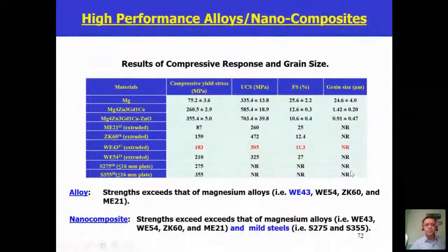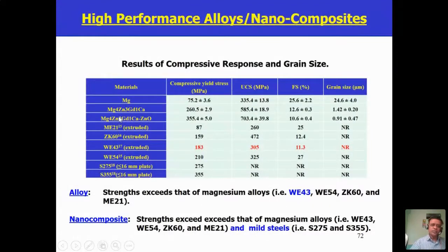We also develop new materials. Now this slide, for example, shows we developed a material with zinc, gadolinium, and calcium. And you see this property, 260 megapascal, 585 megapascal, and failure strain in this case does not go up, but it stays beyond 10%. And the grain size is also very small. So what is the importance of these numbers here? Because these numbers from this material exceed the properties of WE43 magnesium alloy, which is used for aerospace application. And this material, you can make it very cheaply, rather than paying a high price for commercially available alloy.